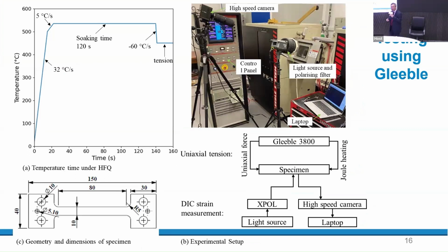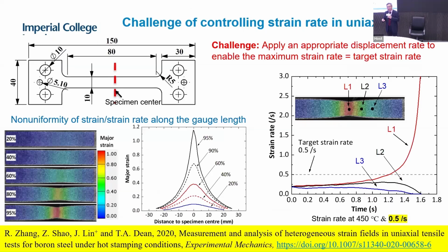Okay, then we do the uniaxial tensile test. For the uniaxial tensile test, previously we mentioned we need to control the cooling rates. This is very important. The Gleeble can do this very well, and then we use the Gleeble to do this kind of work.